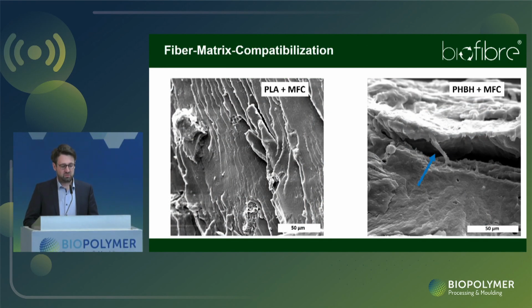2023. What we saw as well is that once you introduce just the nanocellulose or the microfibrillated cellulose into the binder systems, you have something like voids between fibers and matrix. So one of our main goals was to compatibilize in the right way. So sometimes you need the voids, sometimes you don't need the voids, depending on mechanical requirements, depending on biodegradation. So there is no bad material, there is other materials.